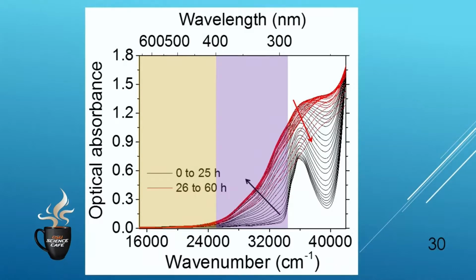Now, this yellow region is the visible region. And you see there is a little bit of increase in that region. That's the yellowing of the polymer. But if you look at the whole UVA regime, we see a significant increase in the carbonyl density. Now, you see a major band here. This major band is intrinsic to the polymer, but it's not really much excited by the UV light, okay? But the carbonyls do.